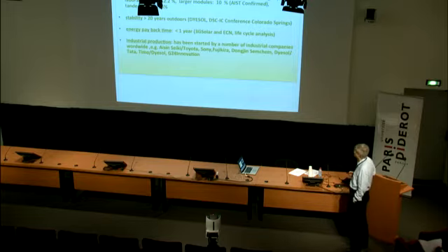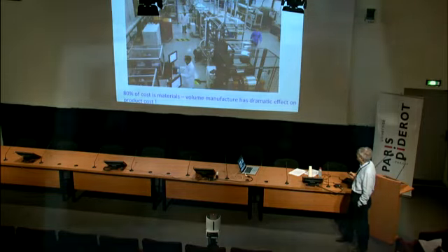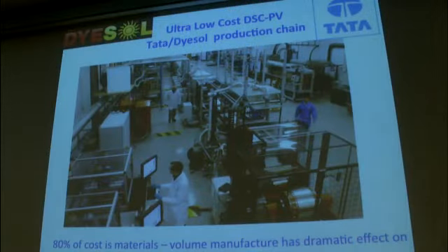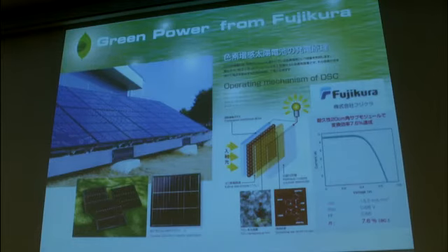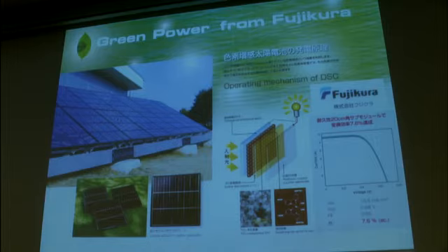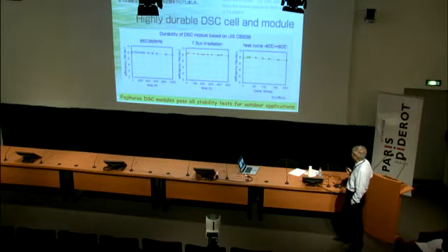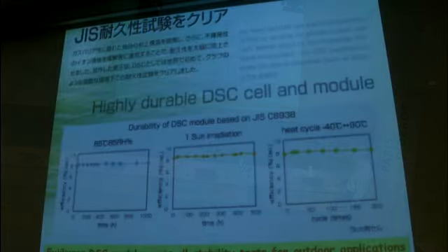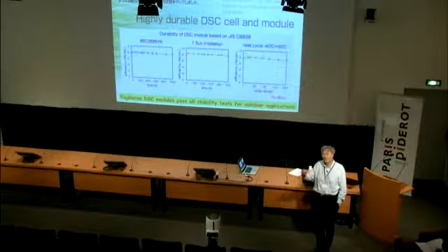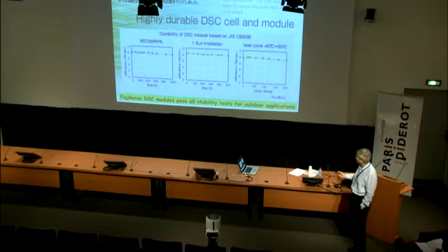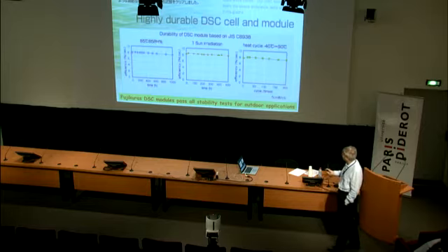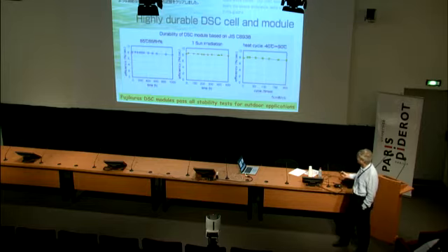There's no doubt. And so here's the Tata Steel plant. This is in Europe, in Wales, being built. Fujikura has announced mass production. These are the dyes, the red and the black dye. And these cells are durable. They fulfill all the severe tests that a module has to undergo before you put it outside in the sun. This is the 85/85 test, stable at 8%, this module. So that's 1,000 hours, 85 degrees centigrade, 85% relative humidity. One sun irradiation, that's easy to meet.